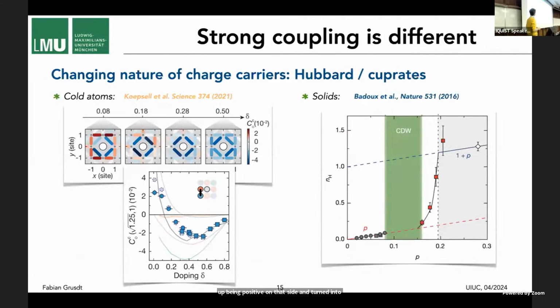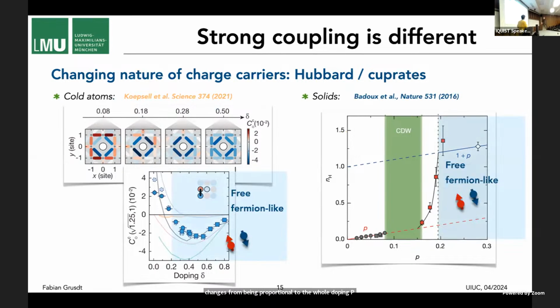So they looked at this in more detail. This is the string correlator right next to the dopant as a function of doping, and you can see this guy changes sign again around 20% doping. And so really around 20% doping, something seems to happen, and that's actually not new. If you look at the condensed matter perspective, it's very well known that around 20% doping you have the superconducting dome, but also that the nature of charge carriers changes dramatically. So here is a measurement of the Hall coefficient. This tells you basically the density of charge carriers, and you can see it changes from being proportional to the hole doping p to something proportional to 1 plus p, around 20% doping.